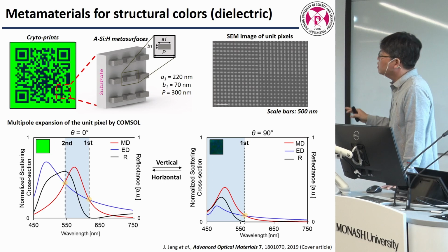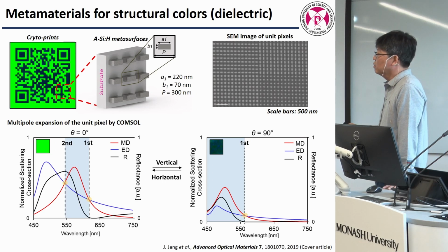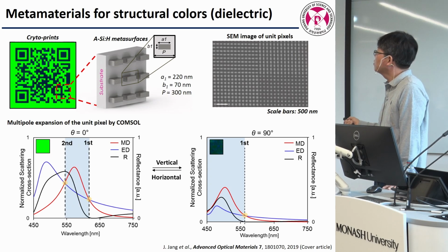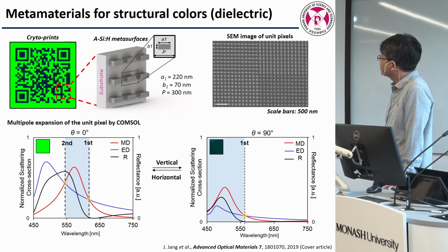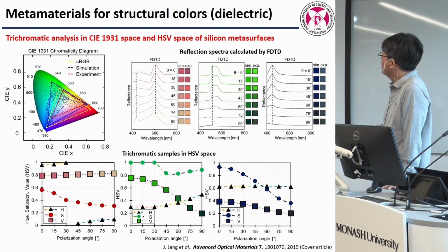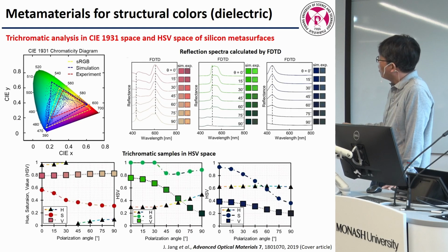So people are now trying to use dielectrics, which have less loss in the visible. Silicon, gallium nitride, they can also make color. But rather than plasmonic resonance, here the Mie resonance is being used. But anyway, the good thing is we can control the color. We can make the color. So this is a simple light green and dark green from silicon nanorods, and red and blue are doable too, and the color map is pretty expanded, and the hue saturation value is good. So humans can feel this is a good color.